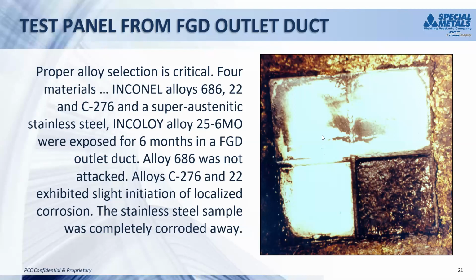We installed a 4-sample test piece with 4 alloys to see how they would perform. The upper left-hand sample is alloy 686. The other 2 that you see adjacent to that are 22 and C276. In the lower right-hand corner, there was a sample of a superaustenitic stainless steel, Incoloy alloy 25-6MO. After 6 months, you can see that that sample has completely corroded away.